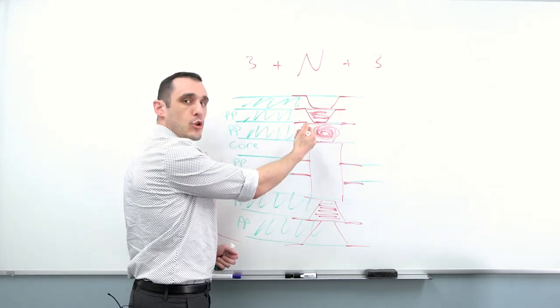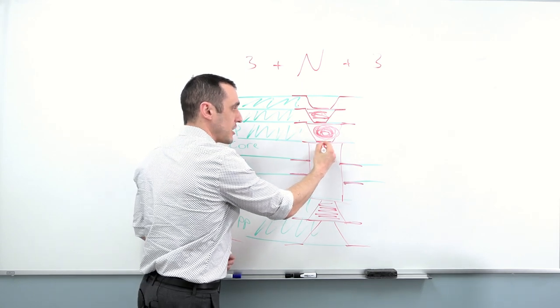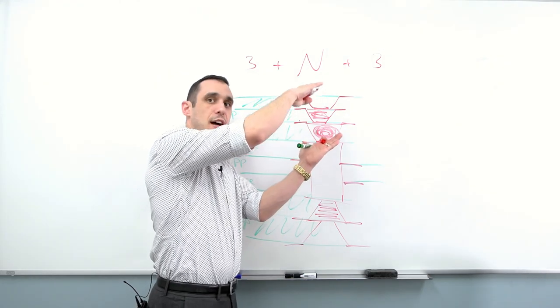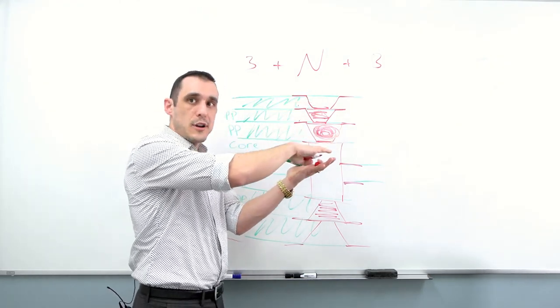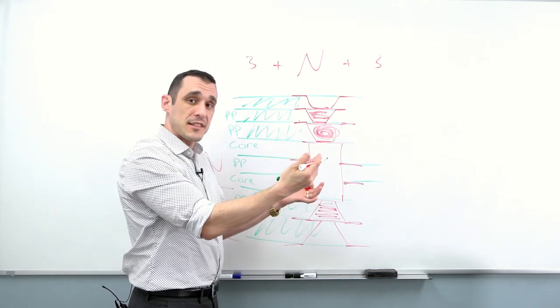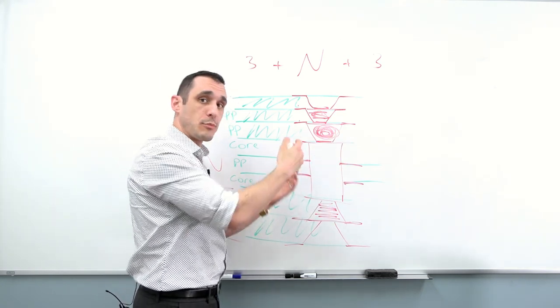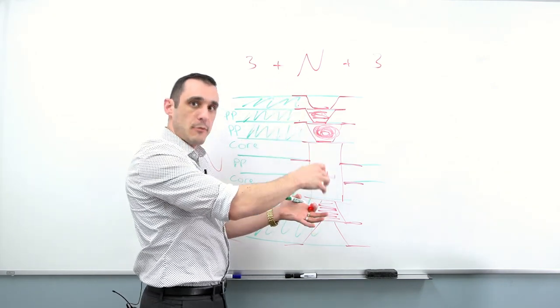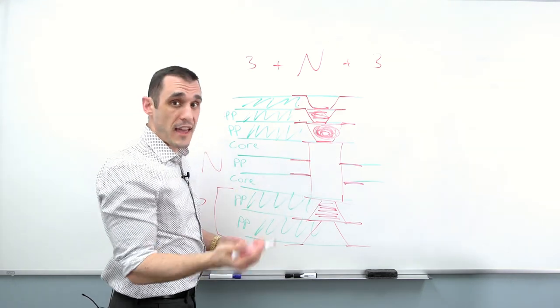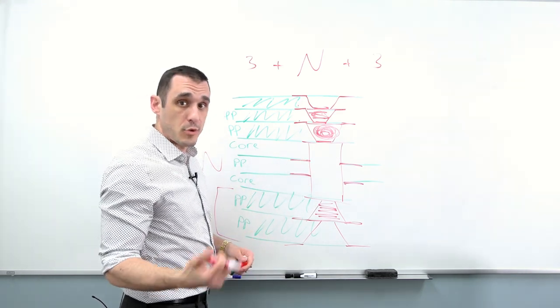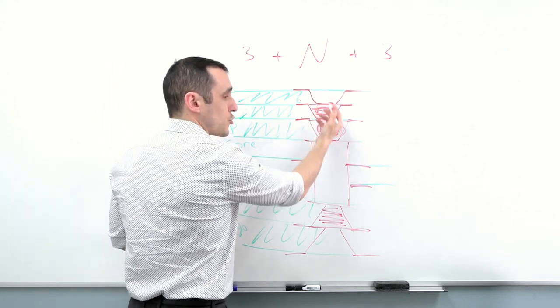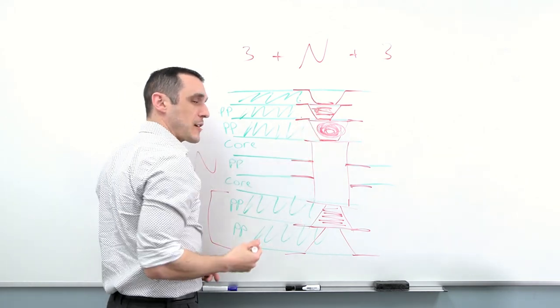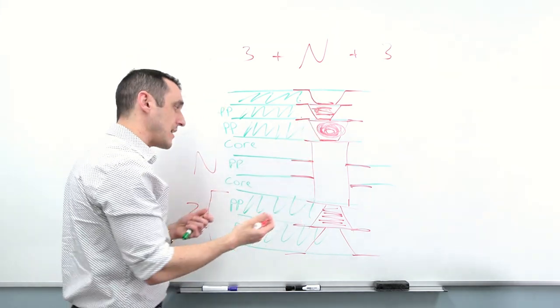Eventually when the layer stack cools down, the crack that arises at the joints can allow the copper to reconnect when the board cools down after reflow, and so it looks like there isn't a defect. However, later, if the board heats up and the prepregs and core all expand, that would lift the copper up and cause the defect to reappear. So the board could fail mid-operation when it's put into the field. For that reason, you may see this drawn like this, however, that doesn't necessarily mean you can always stack these microvias like this when you're actually creating one of these stackups.